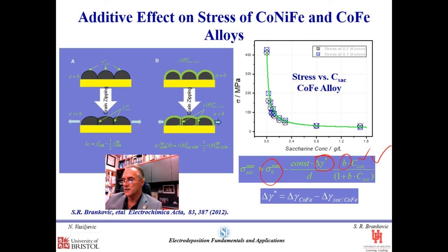Delta gamma star is a thermodynamic quantity which defines the difference between the surface energy reduction for the surface without additives and the surface with additives, minus the reduction of the grain boundary energy for the surface without additives and with additives. And the model explains the data very well, as is shown here, and so you can read more details about this effect in this publication.